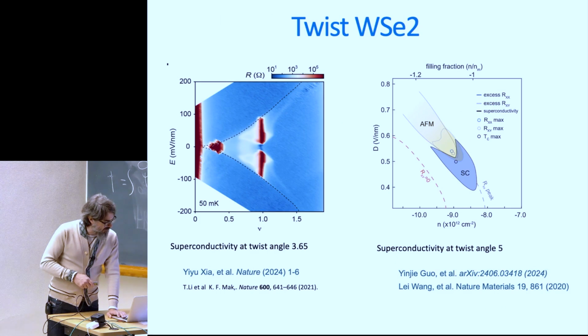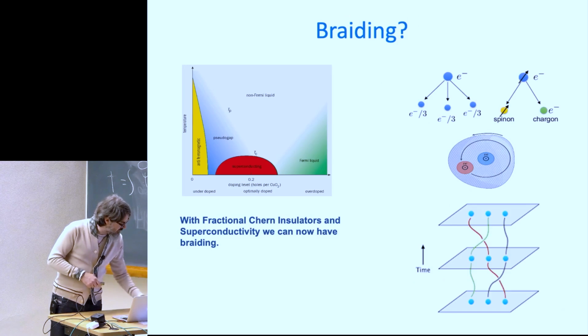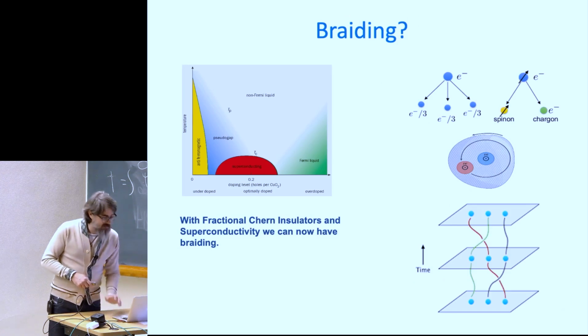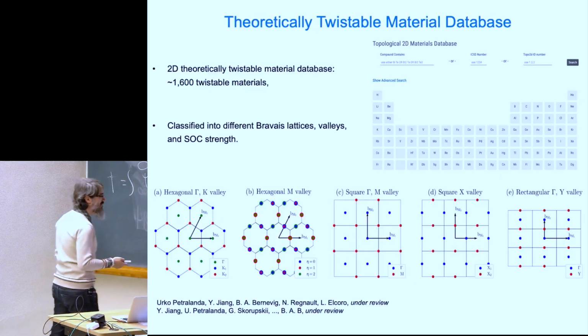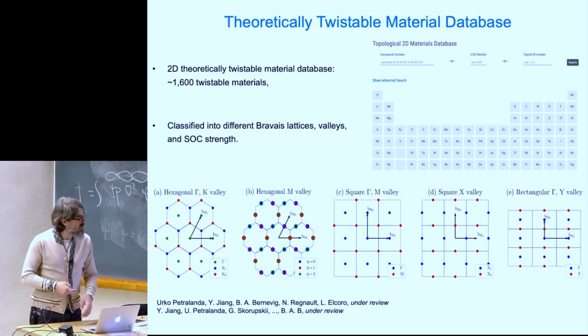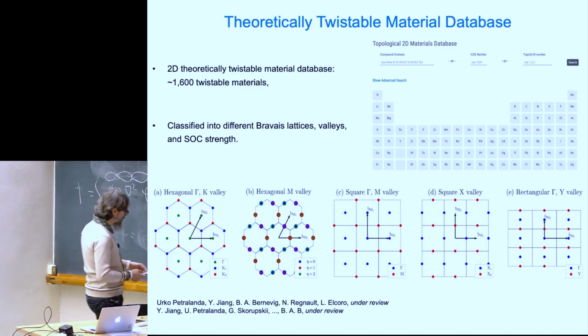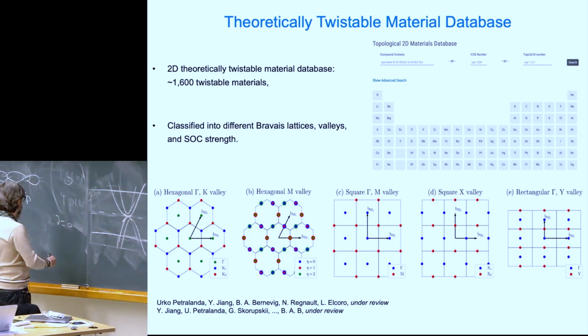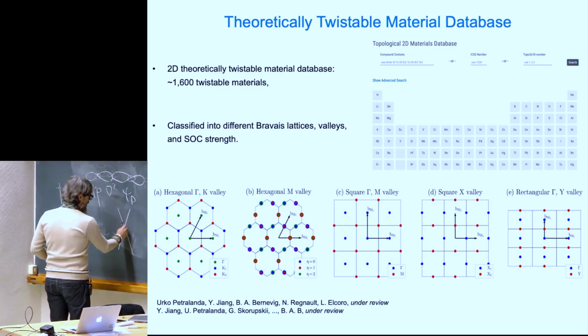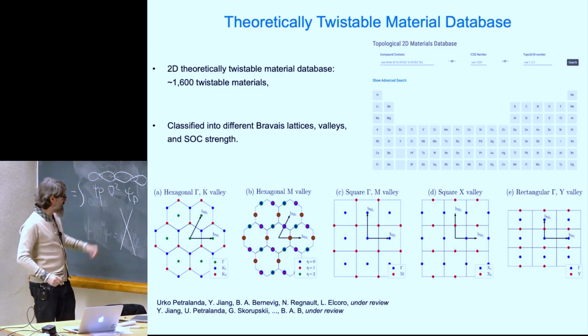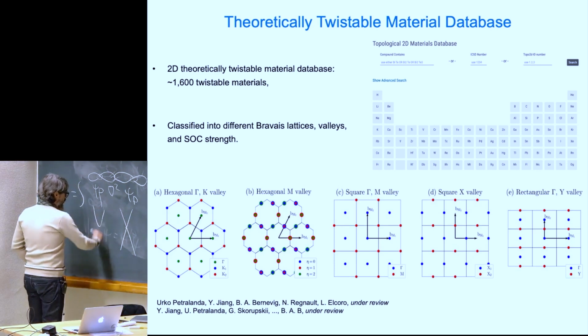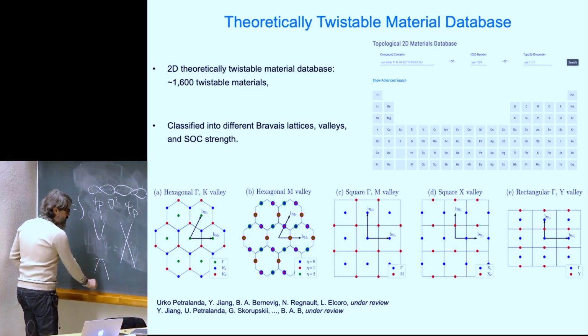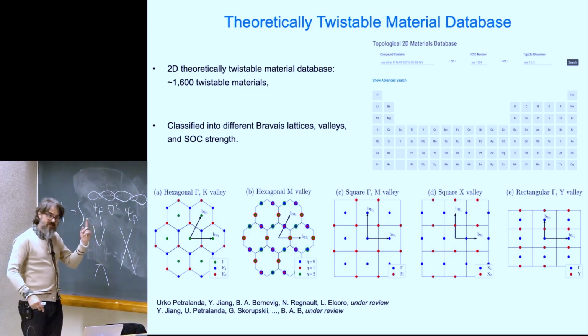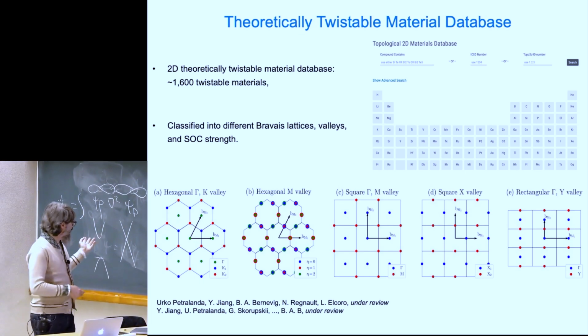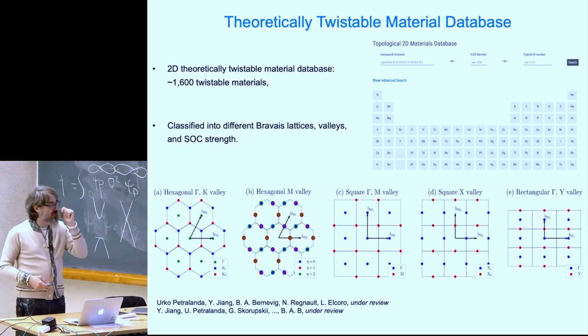And the last thing that I wanted to show you before I close, because I think I'm running out of time, is the fact that this is just the beginning. So the reason why this is just the beginning is the following. So far, all these twisted samples were just made to be twisted at the K point. So for example, graphene had the K point that I then twist. MoTe2 actually also had the K point, but its band structure is gapped, but it's also the K point. Graphene had no spin-orbit coupling. MoTe2 had Ising spin-orbit coupling.